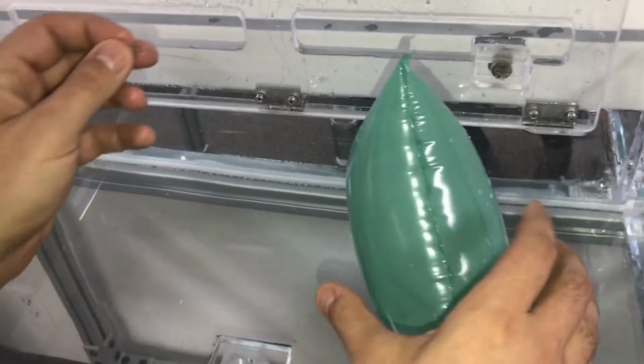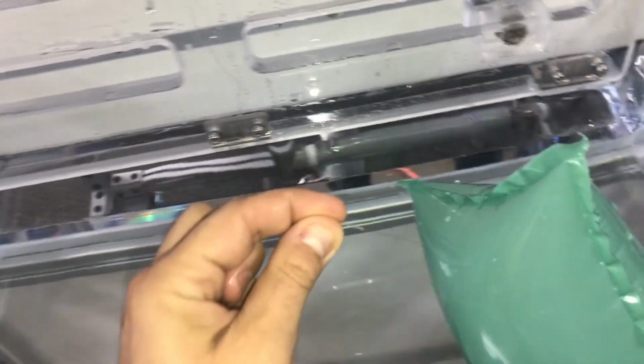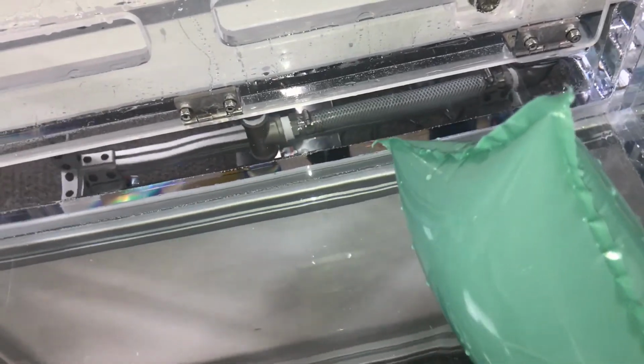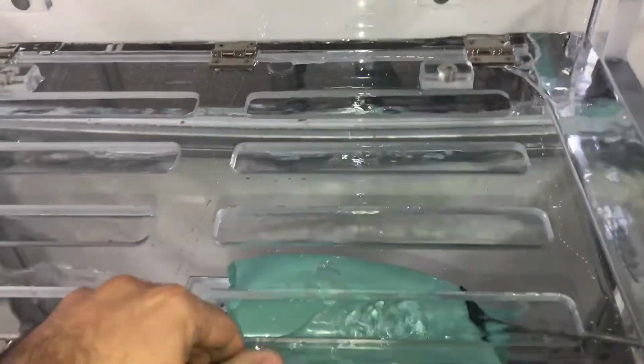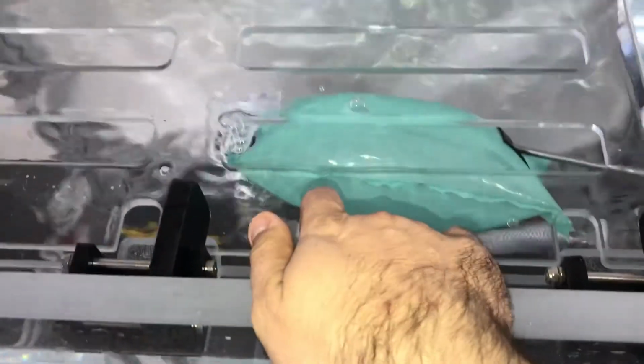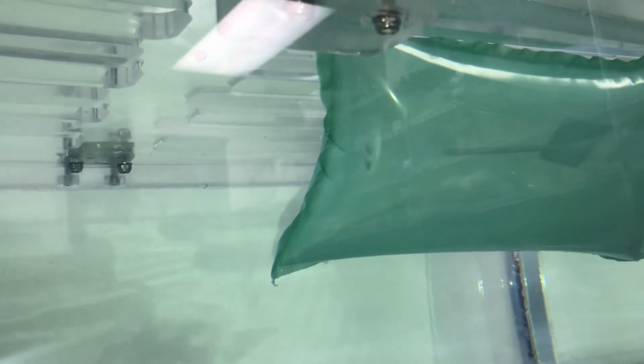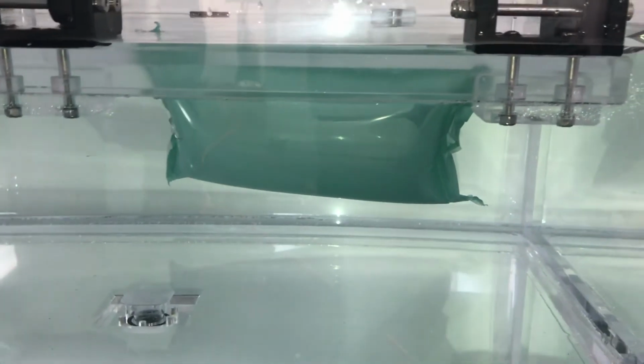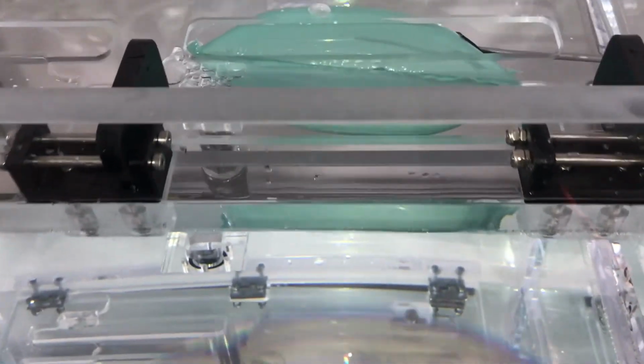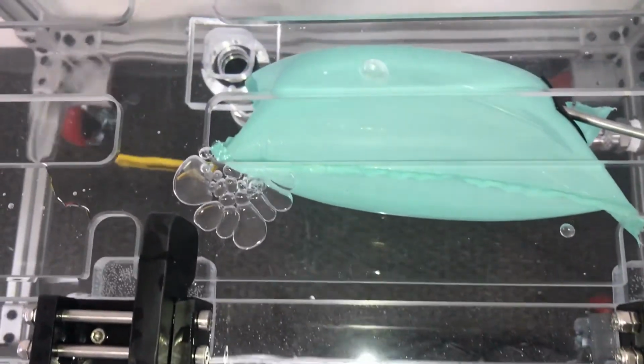And this is an acupuncture needle, and this needle is about 8/1000 of an inch in diameter. So this means that we have an 8/1000 of an inch diameter hole inside that package. And now you can see that there's a continuous stream of bubbles coming out of the package and out of the hole where we punched the hole with that acupuncture needle.